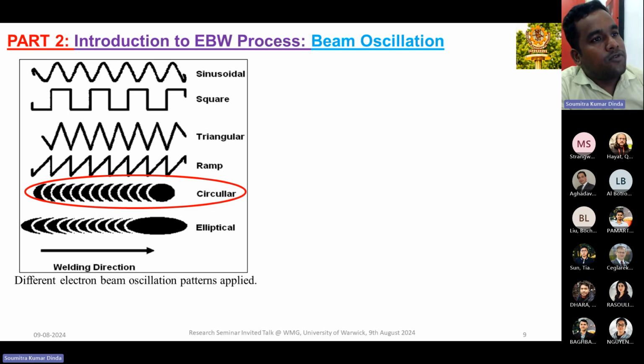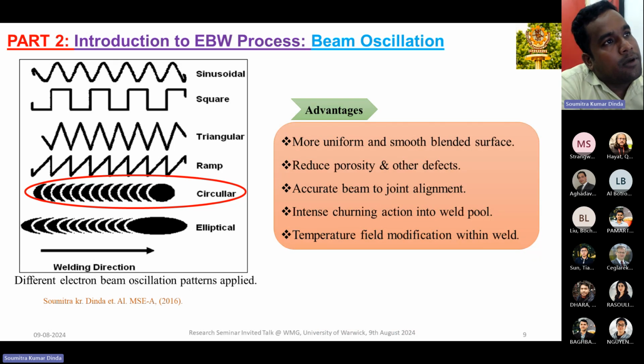So from the literature, we found that if we use the beam oscillation, we will get this type of additional property compared to our without oscillation condition. Suppose a more uniform and smooth microstructure, reduced porosity and other defects, and this point. So for our study, we will justify each and every point, whether all these points are matching or not.